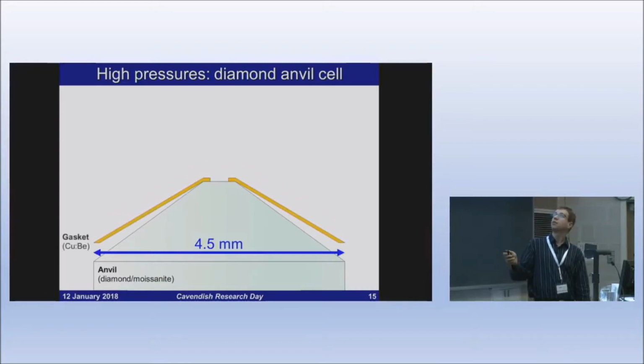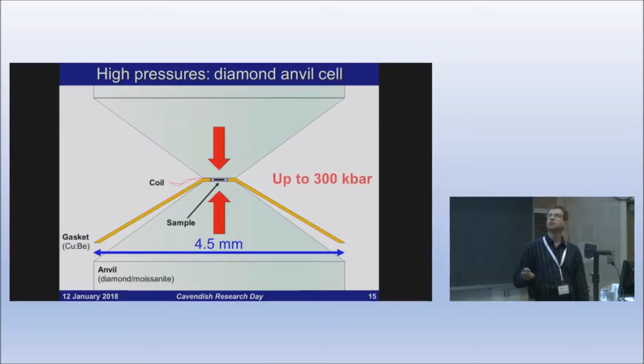We place a hard metal gasket on top with a hole into which we insert our coil and our sample. This is the setup. We'll hook this up to an oscillator in order to measure the skin depth of the sample. We fill the hole with pressure medium, and we squeeze together with another anvil. And so by changing the force that we apply on our cell, we can tune the pressure inside up to 300 kilobar, roughly 10% of the pressure at the center of the Earth. So with just a simple technique, we can get great results.